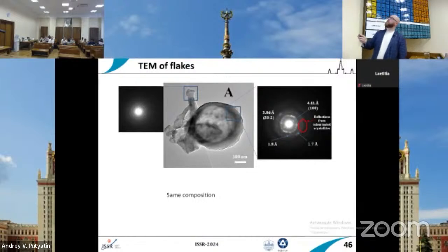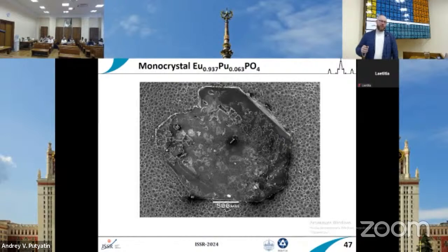And the crystalline structure of these materials is not so good, but the patterns of the crystalline structure are the same as the europium phosphate. So from these investigations, we observed that during the storage of the mixed europium plutonium phosphate, these flakes are just pure europium phosphate without plutonium. So it's like a recrystallization of the material in the solid state. So it was interesting. Actually, there is no amorphization of the material, but some recrystallization on the surface of the materials due to the contact with the humid air in lab conditions, just storage in lab conditions.